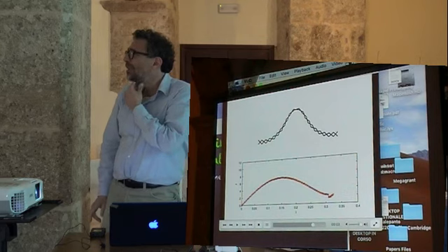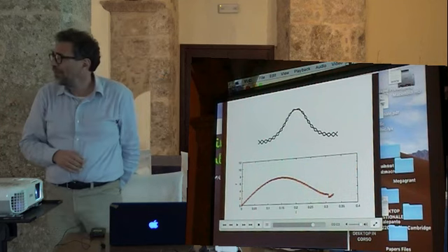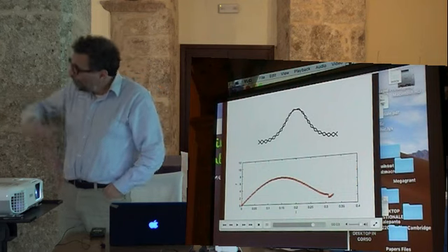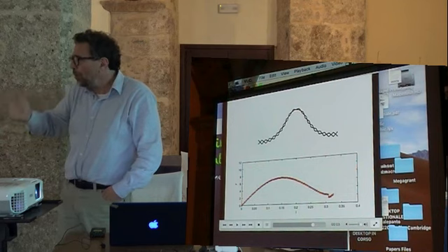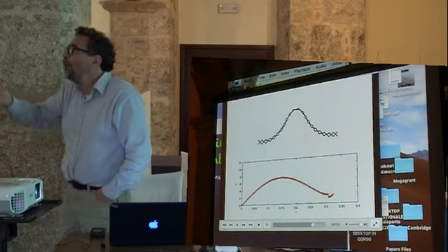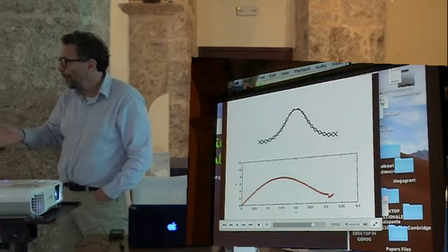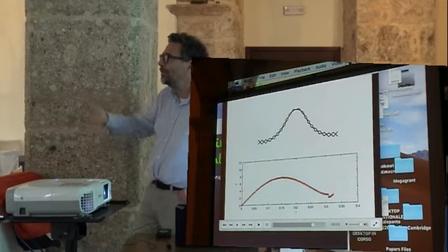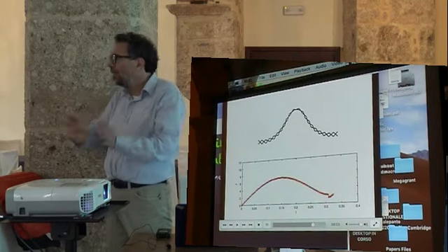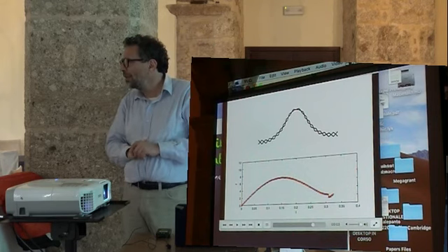Just another question. Your test is displacement control. What will happen if you are force control? I don't know if we have pictures. Emilio Turco, I don't know why, he prefers force-controlled tests, which are very difficult to interpret. We started with force control, and we decided that it is much better to do displacement control. By the way, we got exactly the same results. If you are force control, you cannot pass the peak of force.